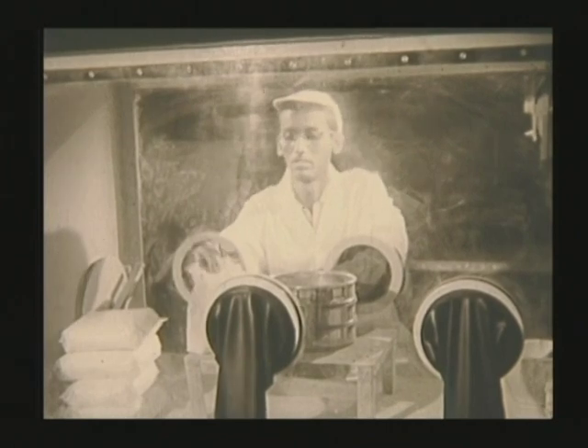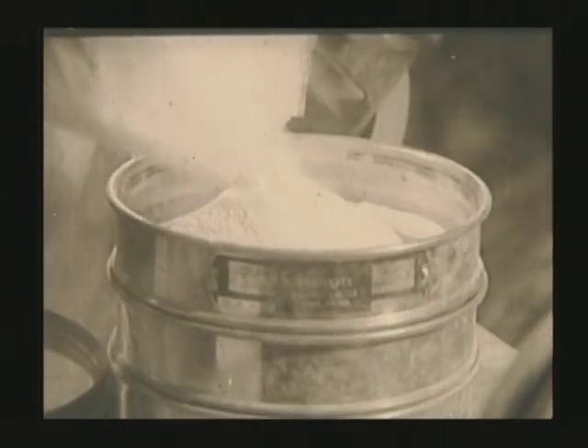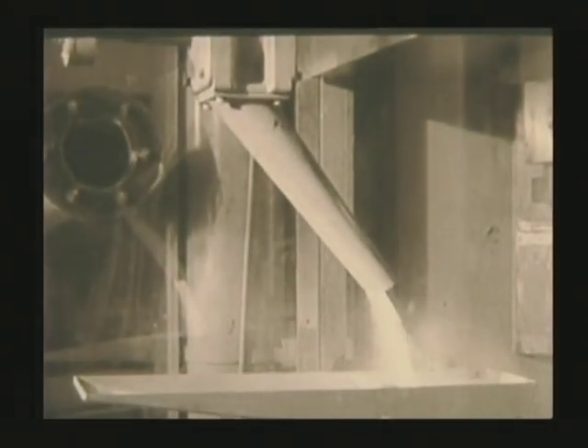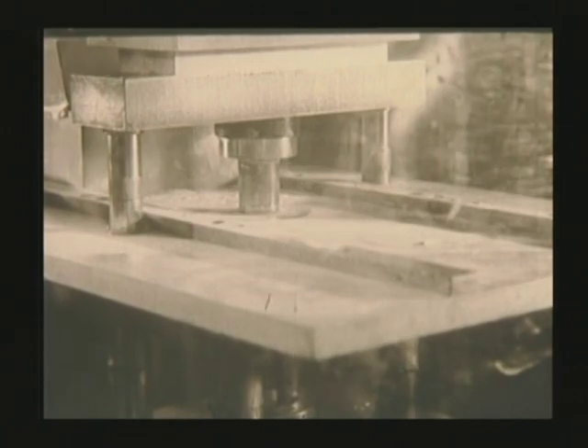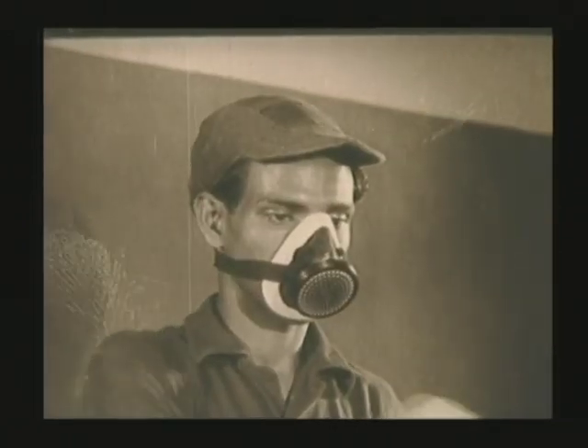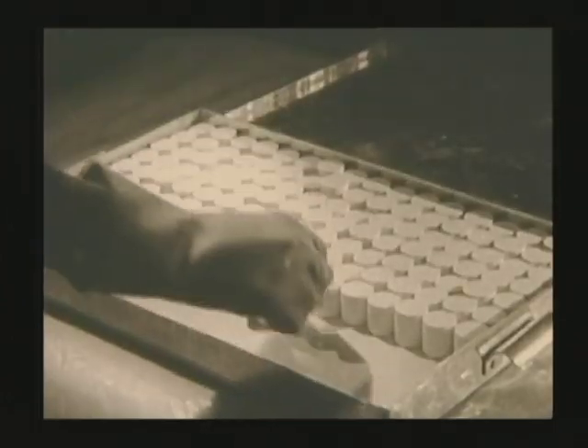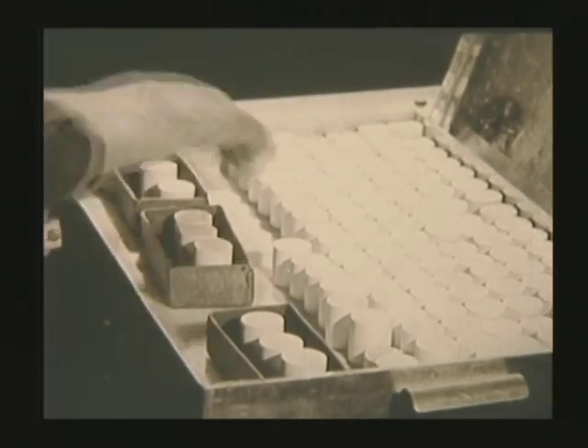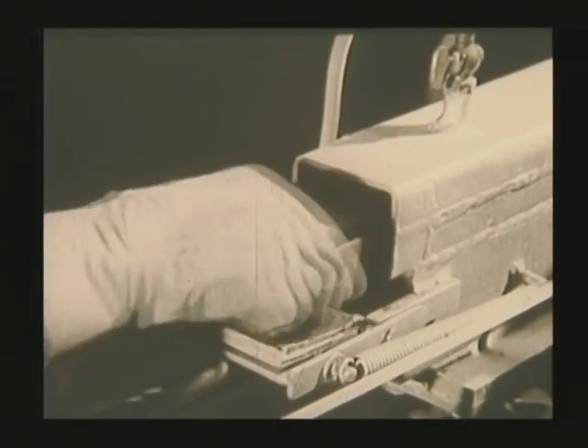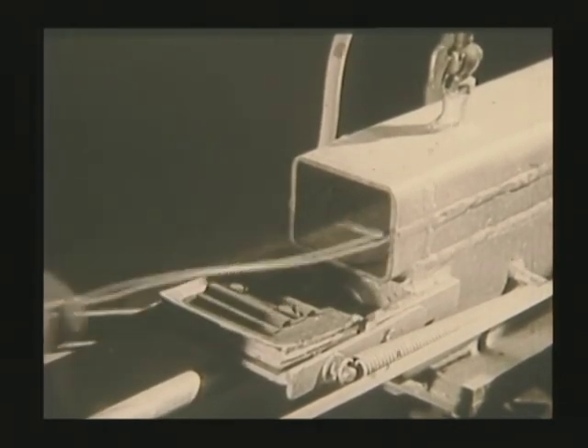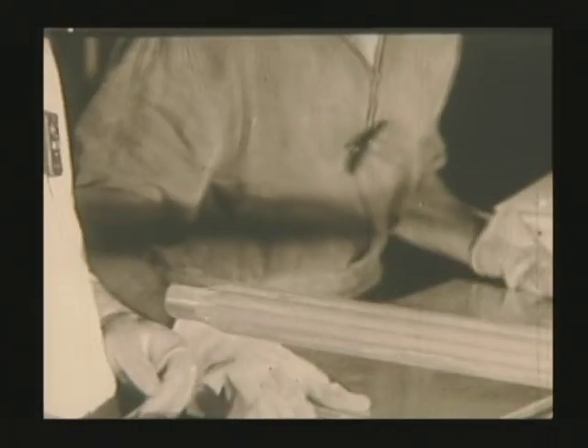Now let us take a look at thorium oxide. Thorium oxide is sieved and then mixed with a suitable binder and lubricant in a glove box. The mixture is then compacted into pellets of specific size on a 200-ton hydraulic press. The pellets are then de-waxed at 500 degrees centigrade and sintered at 1200 degrees centigrade in hydrogen. They are then inserted into finned aluminium tubes. The ends are sealed by welding.